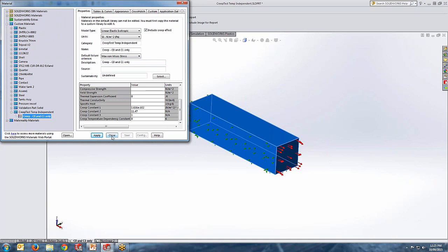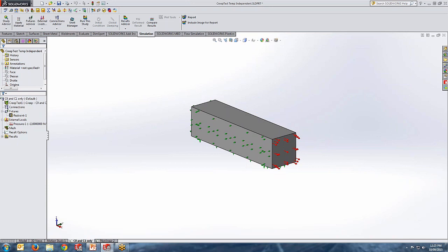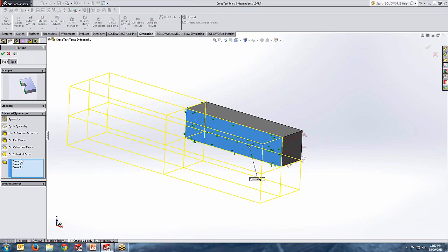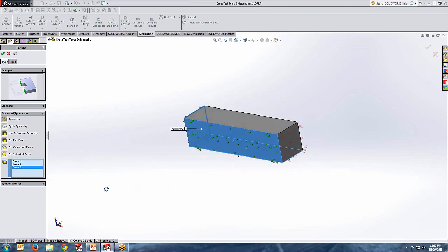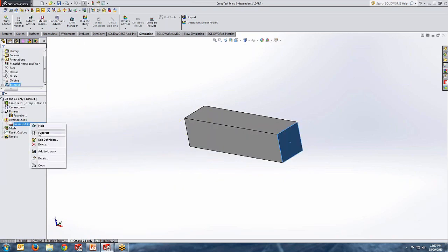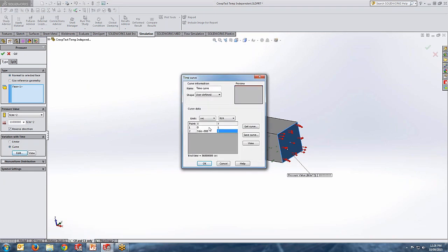Looking at the base study, you can see the same material has been applied, with base information including elastic modulus, Poisson ratio, mass density, and creep effect with my entered values. You need creep test data just like other material properties — elastic modulus, Poisson ratio, mass density — plus what the strain-time-dependent graph looks like. Then you translate that using the equation to get these constants. If your constants and test data are correct, the basis of your calculation is also correct. I have applied symmetry on planes: left, bottom, and back — a full symmetry model — and applied pressure, a normal stress of 110 MPa.